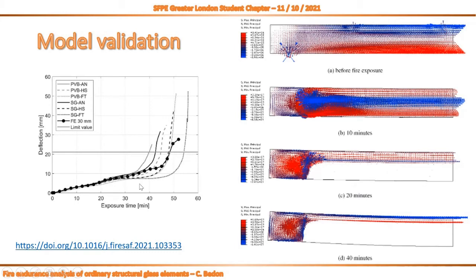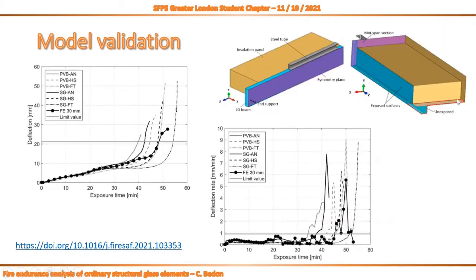The beam, after 40 minutes of exposure, is going to experience more or less 15 millimeters of deflection, but you can see that it is able to sustain mechanical loads in the portions of glass that are protected from fire only. So those portions where we did introduce the insulation panel to avoid very high temperature increase.